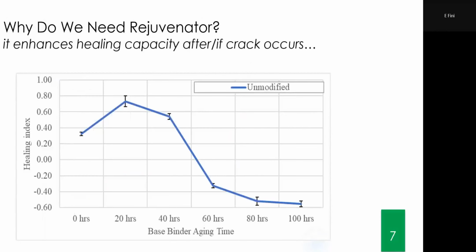Another characteristic I'll show you, which might not be as common in the spec, is healing. If you think about asphalt as something that can heal, then you expect the aged one to heal less, and you want your rejuvenator to give you the healing capacity back. Here, the blue line shows the aging progress. We measured the healing at 0 hour, then 20, 40, 60, all the way to 100 hours. Healing capacity means if you create a tiny crack and let the sample rest, it can heal itself.